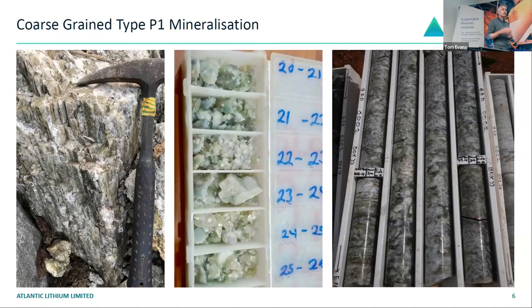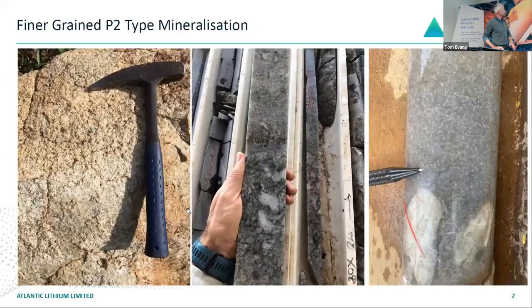SC6 is the terminology, that's 6% spodumene concentrate, rather than having to go through flotation if you've got very fine-grained spodumene, or if you've got other lithium species such as petalite, eucryptite or lepidolite, which are all currently being mined in the market and processed downstream by the converters. But the preference for the converters is for a clean, coarse spodumene concentrate because it behaves well within the kilns, which is the first part of that conversion process. So this is good for us, and it's what drives down our OPEX and our CAPEX.